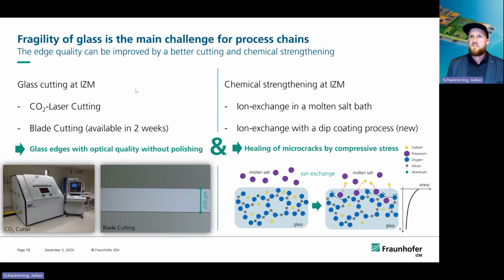Another important thing is the chemical strengthening that we can also do at Fraunhofer IZM. We have an ion exchange in a molten salt bath, and we have an ion exchange with a dip coating process. This is a really new process. With both of them, we can make the healing of the micro cracks by compressive stress. So we can have an ion exchange, replacing sodium ions at the surface with potassium ions. And then the glass, especially the edges, are more robust.